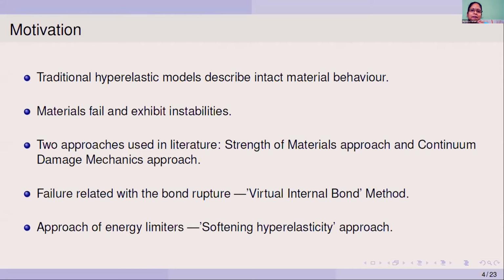A physically motivated alternative to this continuum damage mechanics approach, which models the failure related with bond rupture, called the virtual internal bond method, was proposed by Klein. This virtual internal bond method is a multi-scale method which mixes atomistic and continuum descriptions. The continuum atomistic linkage led to the formulation of macroscopic strain energy potentials, which allow for modeling strain softening and strain localization. This method is very effective at small length scales where purely atomistic analysis is needed.